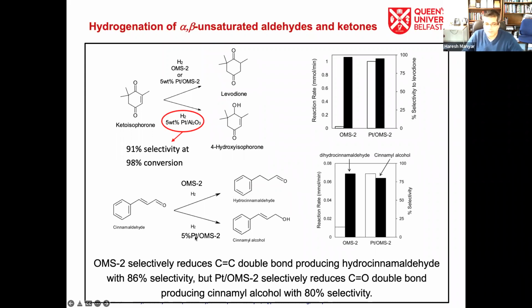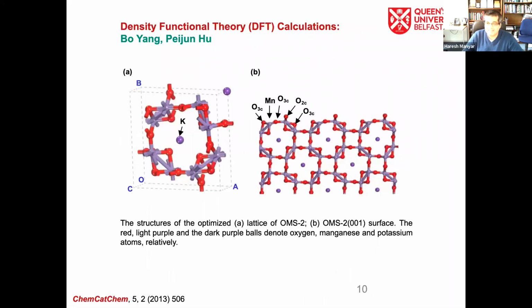And we can also look at the hydrogenation of cinnamaldehyde. Using OMS2 for hydrogenation of cinnamaldehyde, we are getting the opposite trend here. If you look at the reaction at the top, we are taking out the carbon-carbon double bond with OMS-2. If you look at the reaction at the bottom, we are taking out the carbonyl group, and we are getting the reduction to alcohol. So why is it showing different trends, that on one hand we can selectively take out the carbon-carbon double bond, or on the other hand we can take out the carbonyl group? We can tune that. The key lies in the adsorption, how we can tune the molecular adsorption, how we can modify the molecular interaction of the carbonyl group or the carbon-carbon double bond, which lies in the adsorption geometry on the surface.